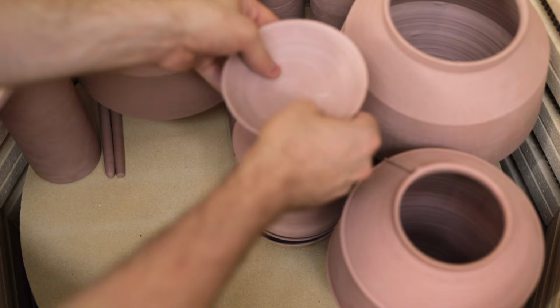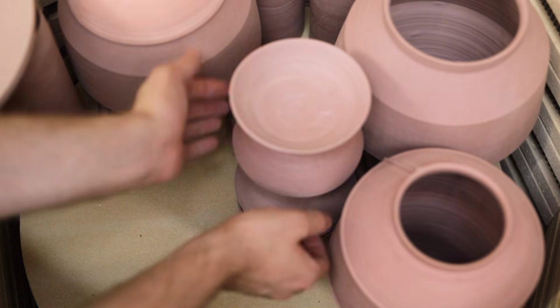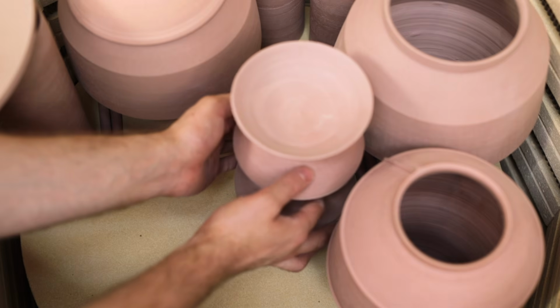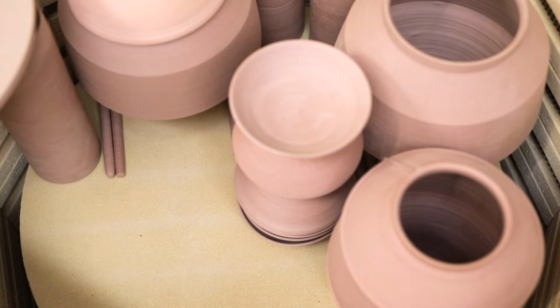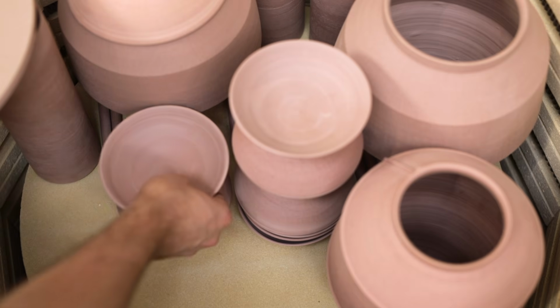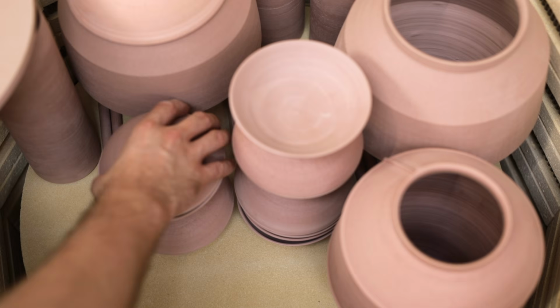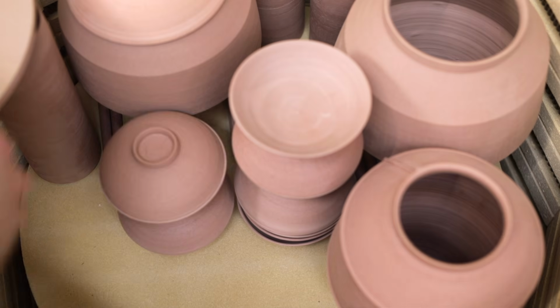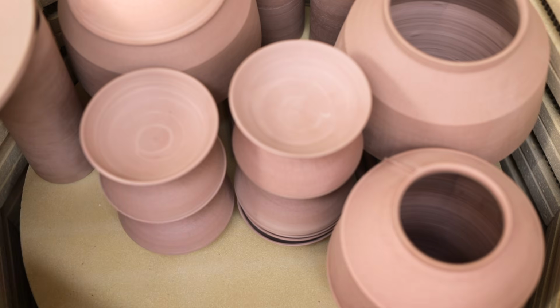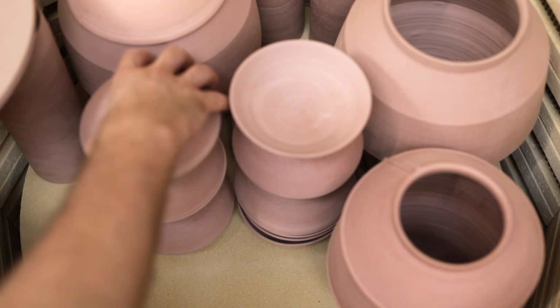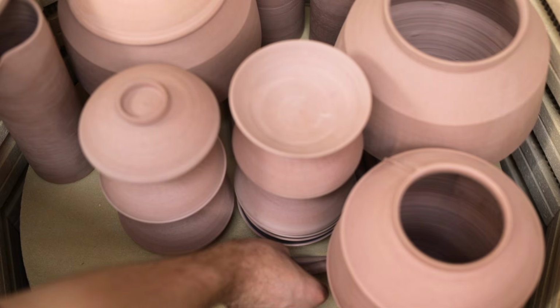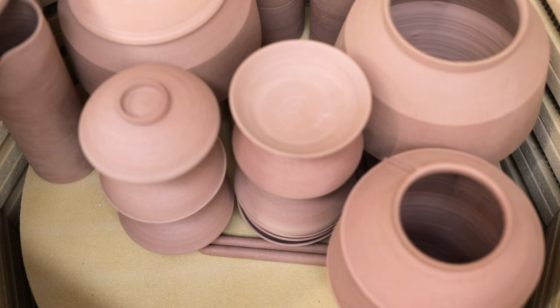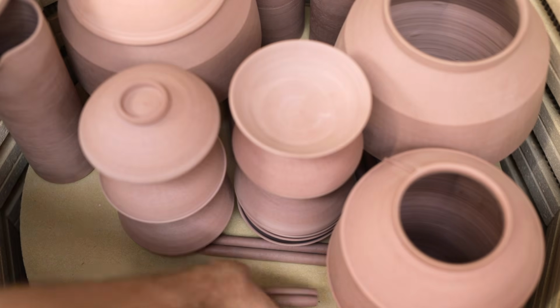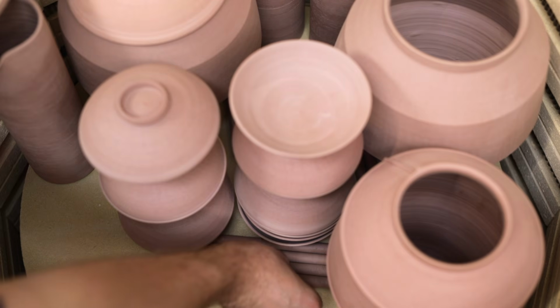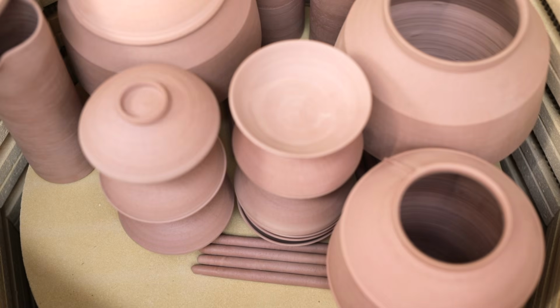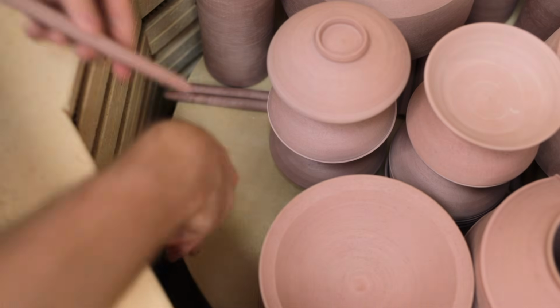And for these bisque firings, I simply pack them as dense as I possibly can, as the more pots I can squeeze in at any one time, the more cost efficient each firing becomes. And kilns actually fire better when there's more inside them, rather than having large expanses of empty air which just need to be heated to 1000 degrees. And this is especially true when it comes to reduction firing in a gas kiln, which is a process that comes a little further down the line. But for now, I just carefully slot the pots into these spaces beneath the bowls and in between vases. I even roll them into place sometimes for those hard to reach areas.